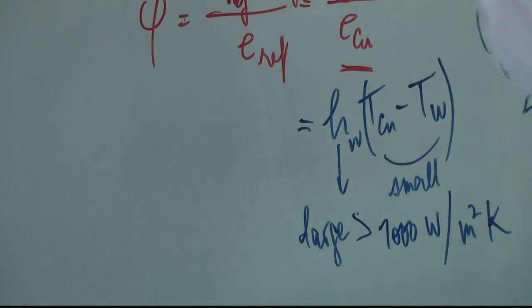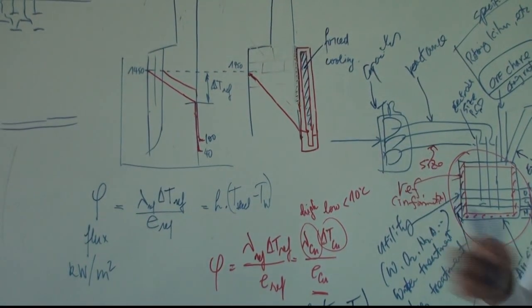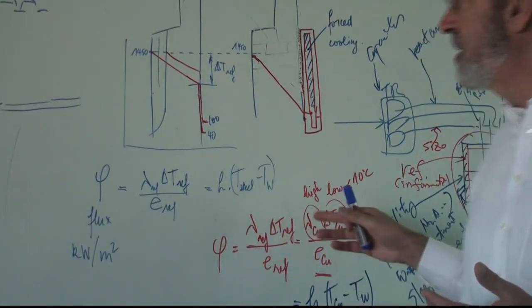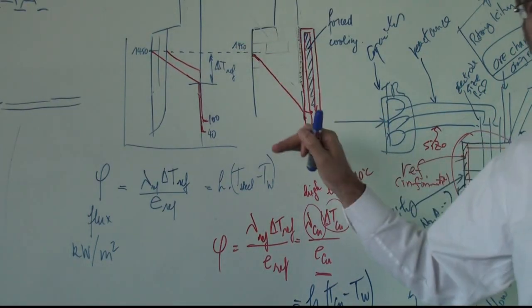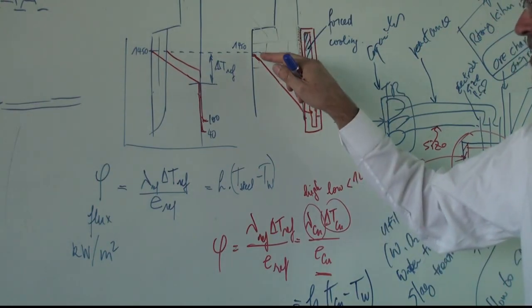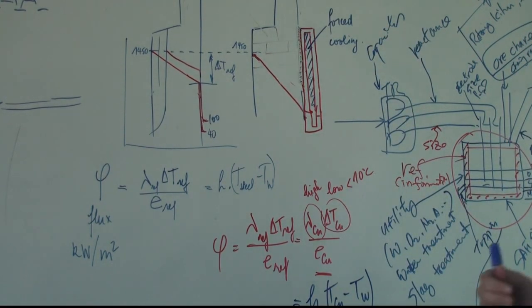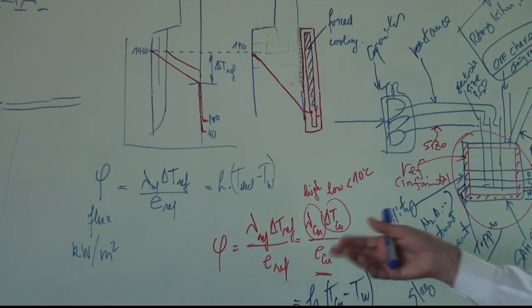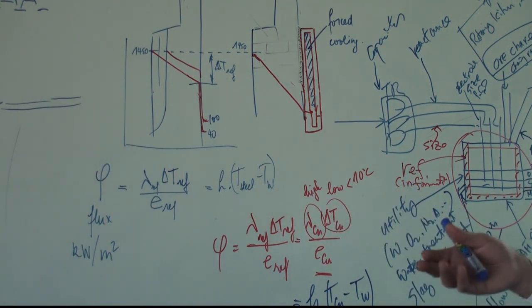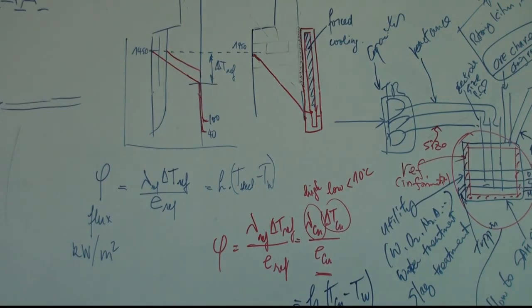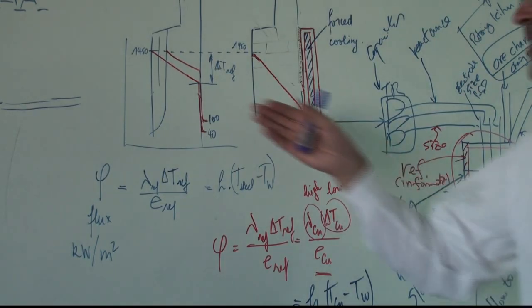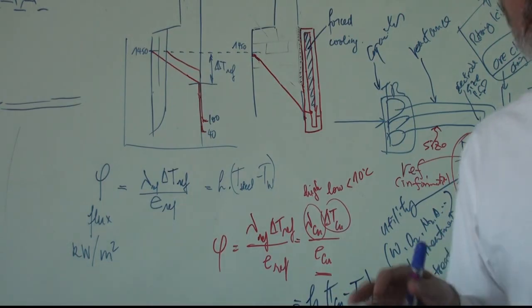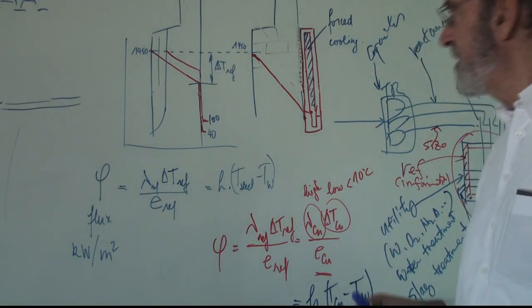So, of course, doing this forced cooling of the wall will at the end increase the heat flux. To protect the refractory, to reduce the maximum temperature of the refractory, requires doubling or more the heat flux, and that means that you accept to have higher heat losses. There is no mystery. You cannot have both no heat losses and the wall well cooled. That's not possible.